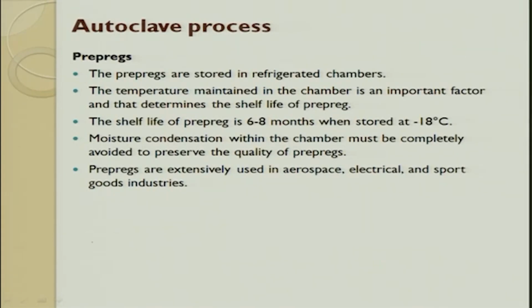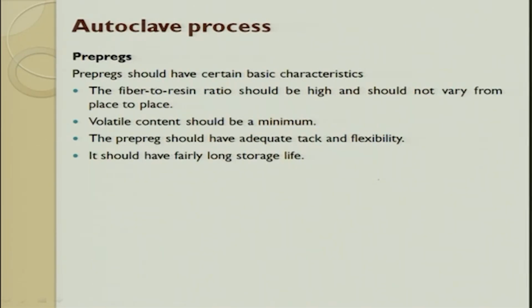They are stored in a refrigerator, because when you expose them to temperature they will cure. So they are always maintained at -18 degrees. They have a shelf life of 6 to 8 months. Moisture condensation within the chamber must be completely avoided to get a good quality output. This is used for various applications.